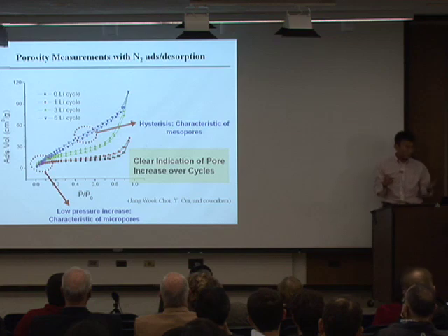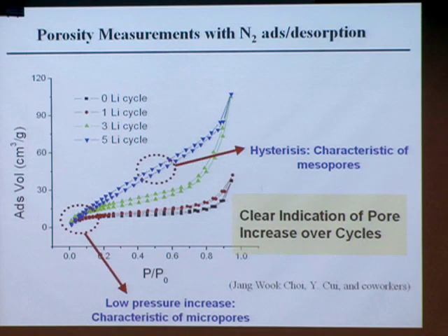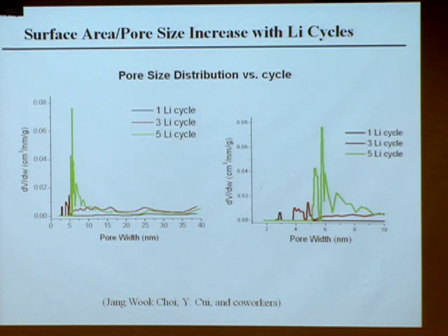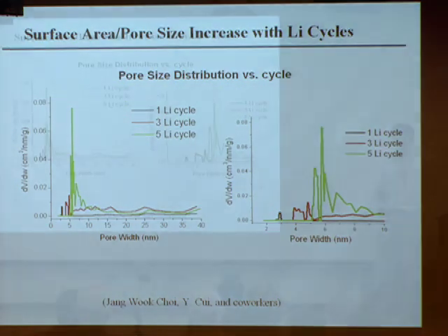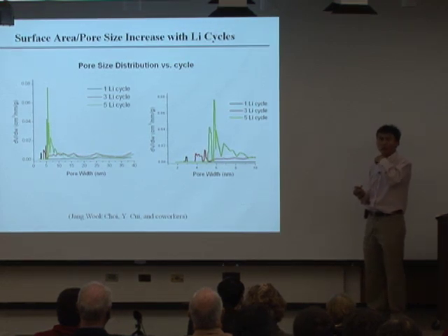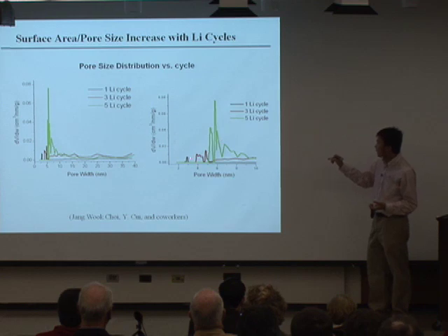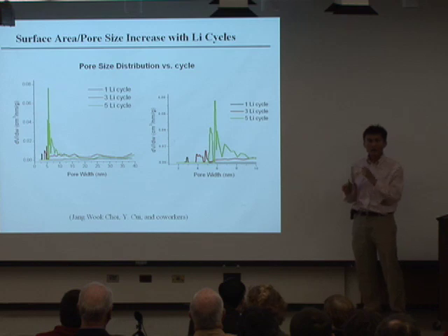So we studied the porosity of this nanowire after cycling by doing the gas adsorption measurement. I'm not going to go into this data. Let me just tell you what we found. So the overall finding is this is the size of the pore. This is the distribution, the number of the pores, for example. And let's zoom in, just look at these areas on the right-hand side. After one lithium-ion cycle, you get lithium in, you take lithium out, you create pores. The pore size has a distribution about, say, 3 nanometer or so. Very, very small pores. And then you can do multiple cycling. You can do 3 cycles, 5 cycles. It looks like the size of the pore shifts to the right-hand side, so becomes bigger and bigger.